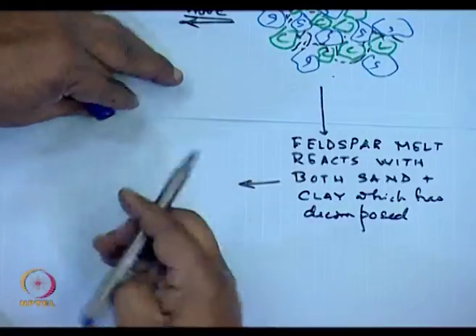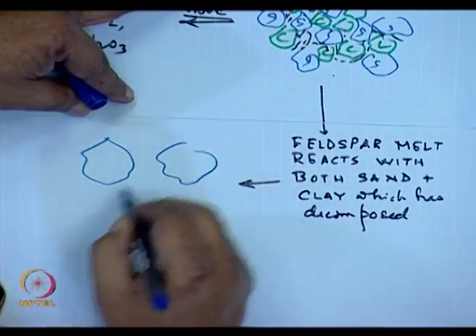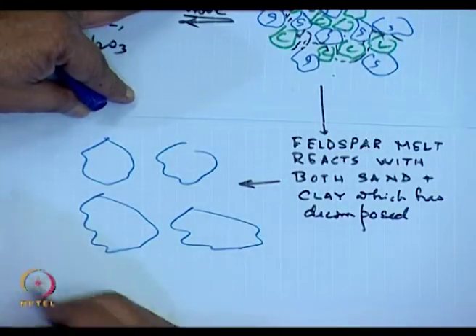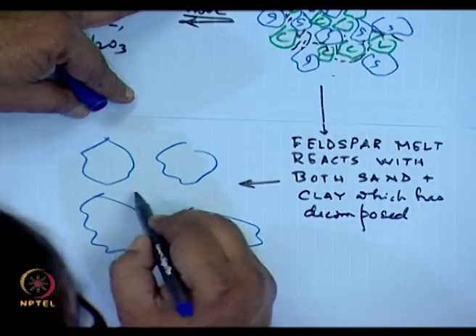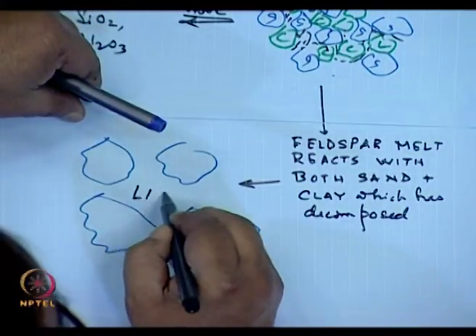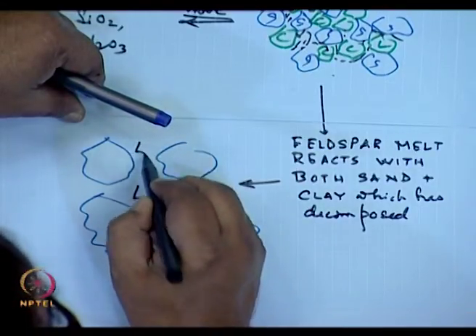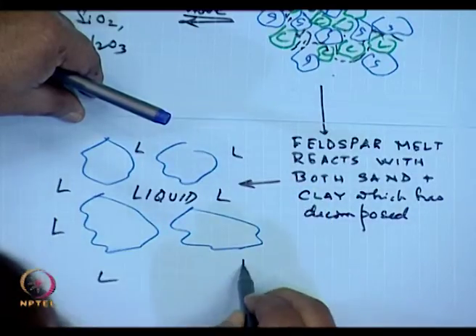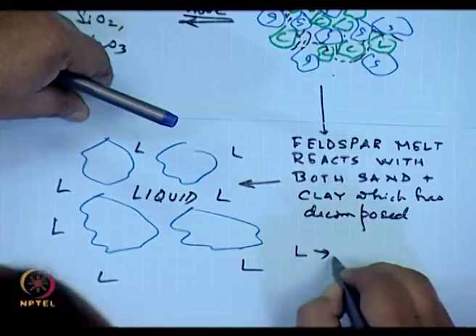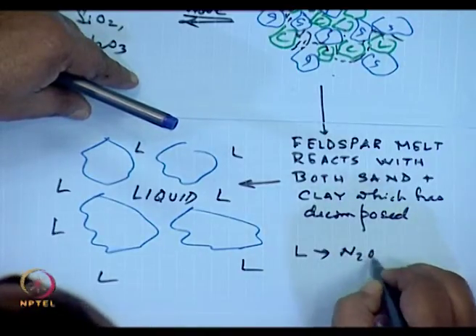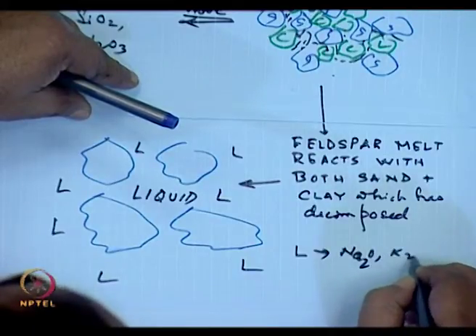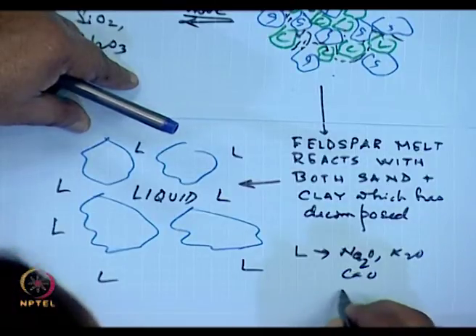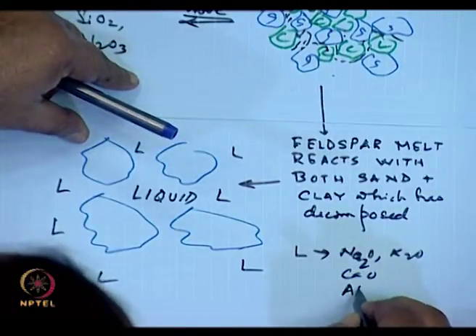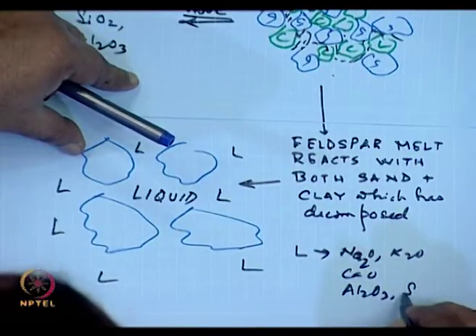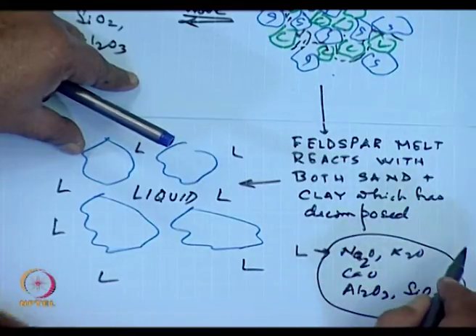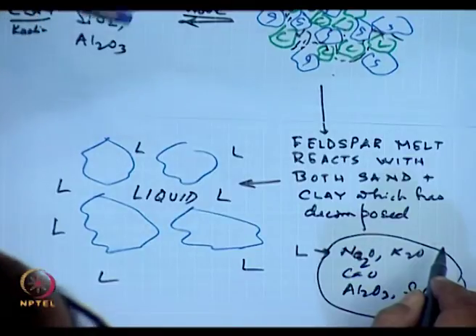Sand is blue, fine. So I'll have sand grains, sand grains, sand grains, sand grains. And there's a whole lot of liquid over here. This is all liquid over here, which is surrounding the sand grains. This liquid is very rich in sodium oxide, whatever is there, potassium oxide, calcium oxide, very rich in alumina, very rich also in silica, all of which have been derived from feldspar melt reacting with the clay.